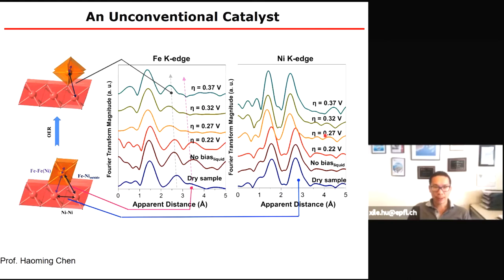And we realize that this is not iron-doped nickel OOH. This is actually a two-component catalyst where we have an iron oxide cluster that is attached to a gamma nickel OOH. Initially, they are kind of separate. But under operational condition, at high potentials, you turn to a so-called corner-sharing. And this process is actually reversible. And so this will be a two-component catalyst.